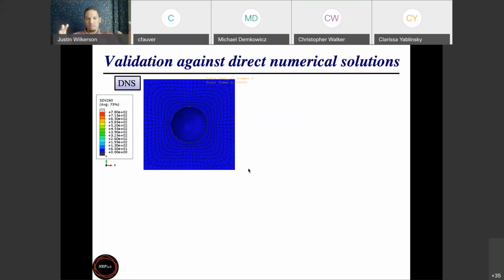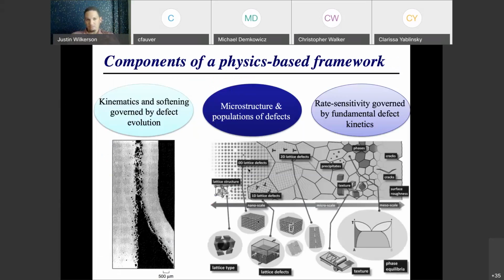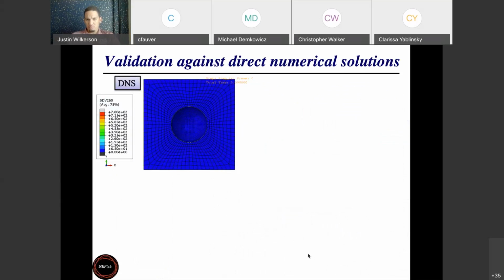So the framework has accounted for the kinematics of softening being governed by defect evolution. So we talked about how in a physics-based way, the porosity softens the elastic constants. In a physics-based way, it degrades the strength of the material. And in a physics-based way, we're able to convert elastic strain into inelastic strain. And then we have all of our kinetics of defects, kinetics of dislocations, kinetics of voids being accounted for in a physics-based manner. We can throw all of that into a framework,